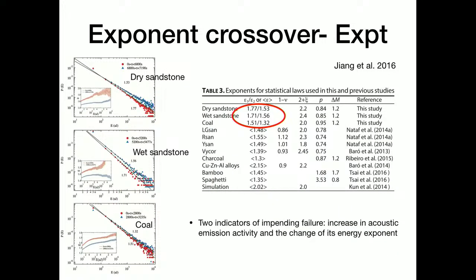So when they look at the power law exponents of these samples, as I said earlier, how do you measure the crossover is also a little tricky, as in what is the boundary you decide that, okay, before this I'll call it off critical, after this I'll call it critical. So what they have done is they have used time as the way to split the data, and they have found that there is a crossover for the dry sandstone that I had shown earlier from 1.77 to 1.53, and similarly for the other materials including coal.